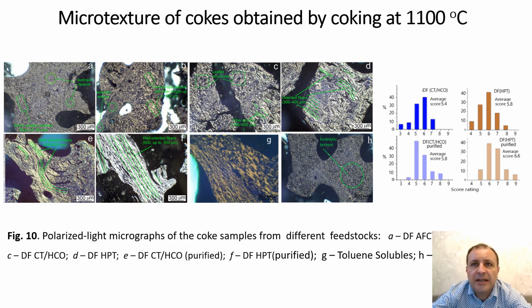Coke samples depicted in figure 10, C, D, and G, obtained by coking of fractions from coal extract in a mixture of coal tar and heavy cyclic oil, and heavy pyrolytic tar, exhibit a more developed anisotropic texture with fibers of 900 micrometers and an average score of 5.4 to 5.8. The average texture score for the coke obtained from the refined distillate fractions increased to 5.8 to 6.6, as can be seen from figure 10, E and F. The increase in anisotropy as a result of purification was achieved through the development of higher scoring texture.